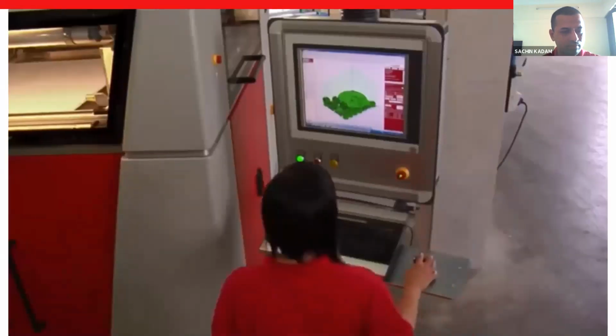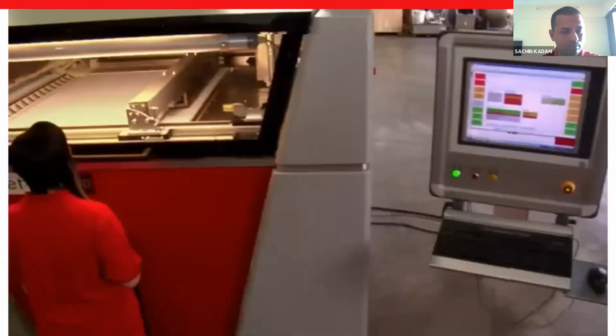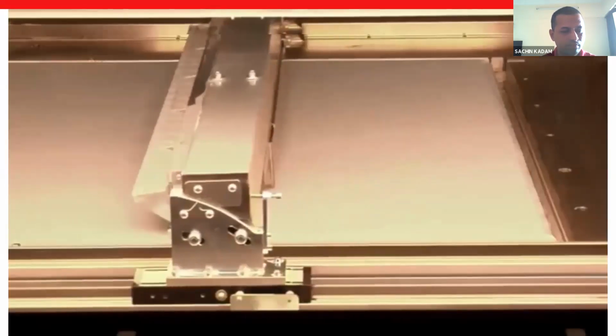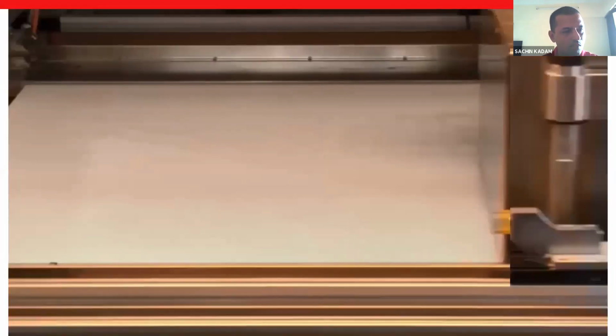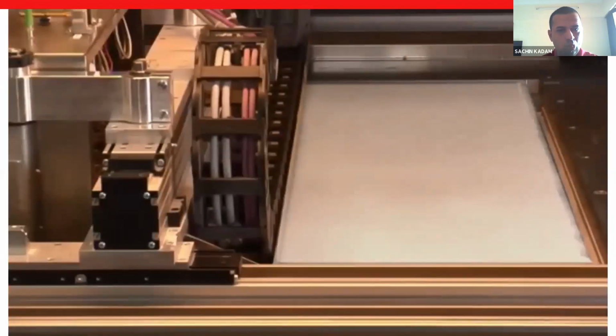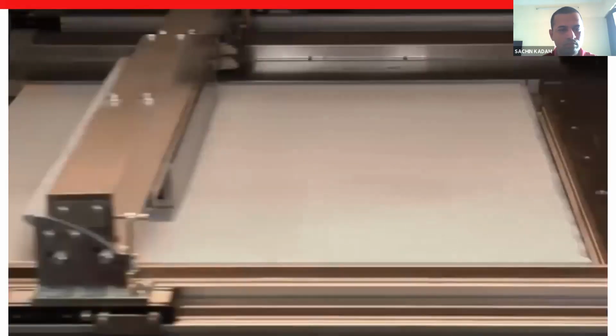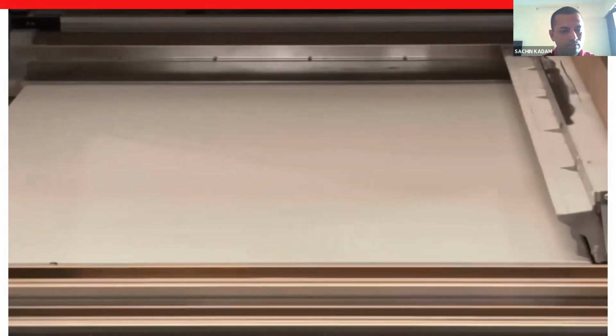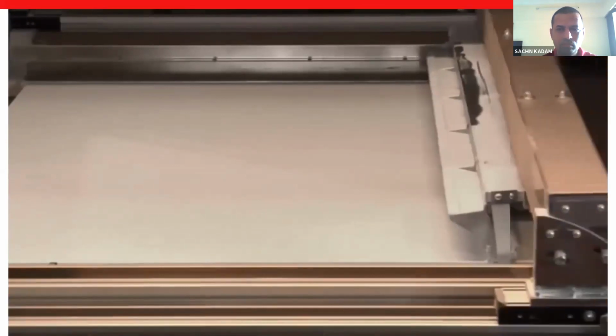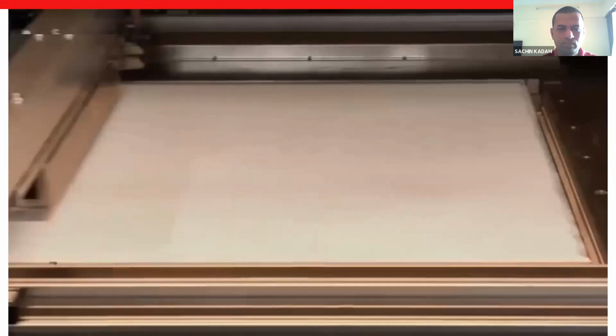The printing process begins when the recoater applies the PMMA powder to the build space in 100 to 150 micrometer layers. At the same time, the printer head selectively doses the binder at the points at which the model is created. The 3D printer's vertical build speed can reach up to 18 millimeters per hour. This layer building method makes it easy to manufacture complex geometries with undercuts in one piece.